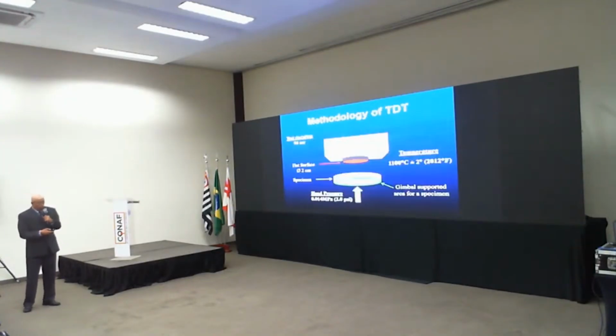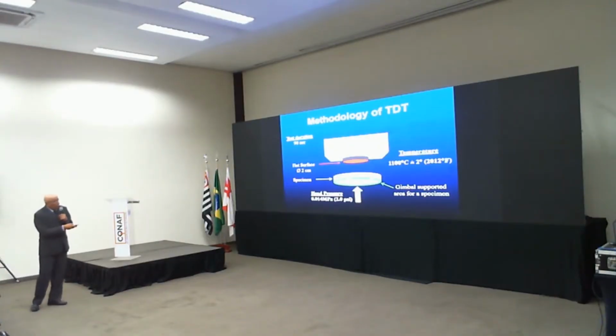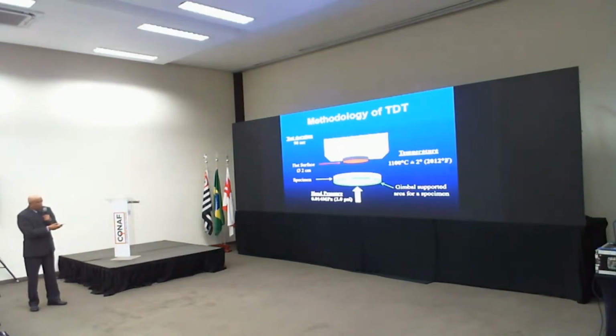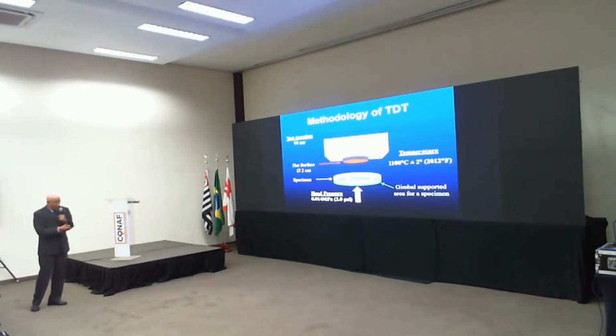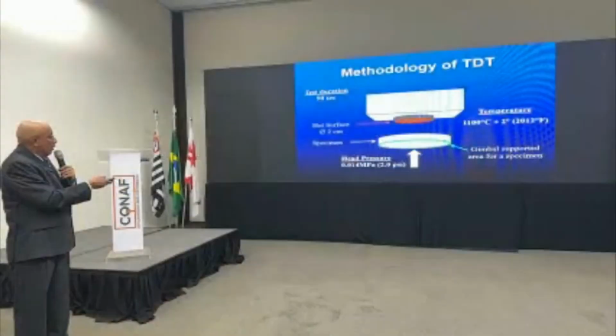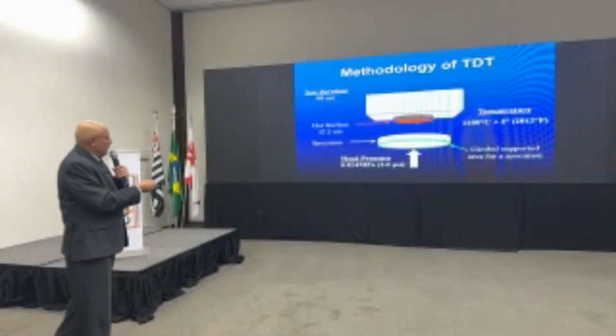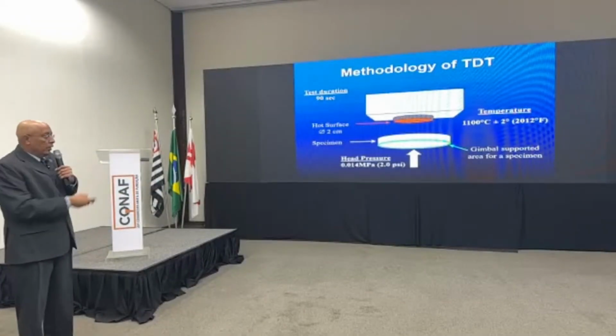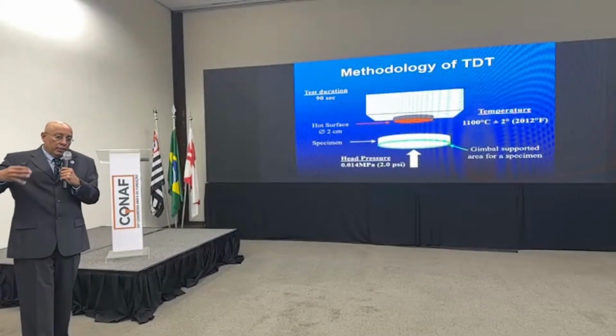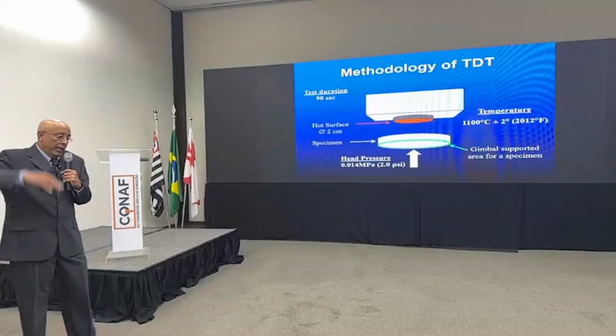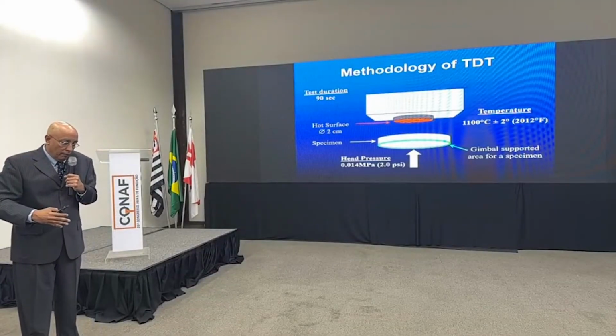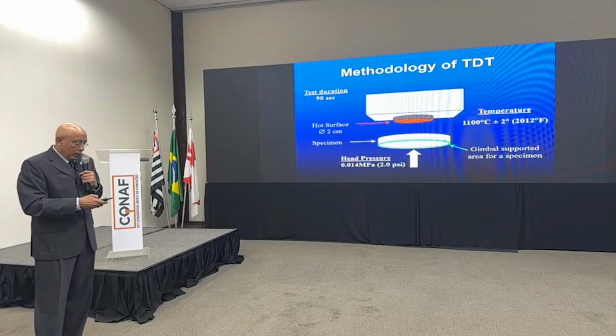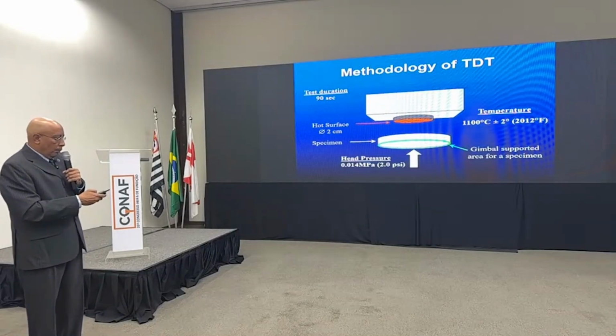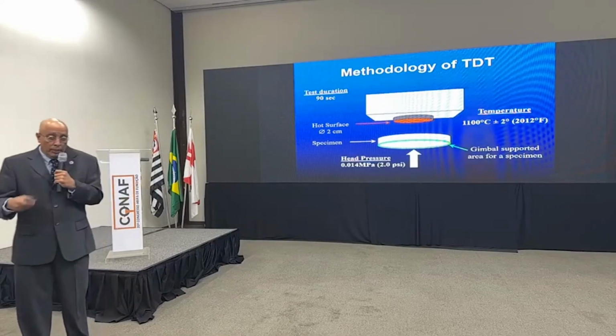So how the thermal distortion test works is that we can support the specimens circumferentially 1 millimeter around the circumference, and that periphery is held on a gimbal to self-align and self-center the cookie against the hot surface that is 20 millimeters in diameter. The test duration is depicted through simulation analysis of the casting. Typically, high head pressure castings take a longer time to solidify, but that is important in this process. And our test temperatures, we can go up to 1450 degrees C if we are representing iron.